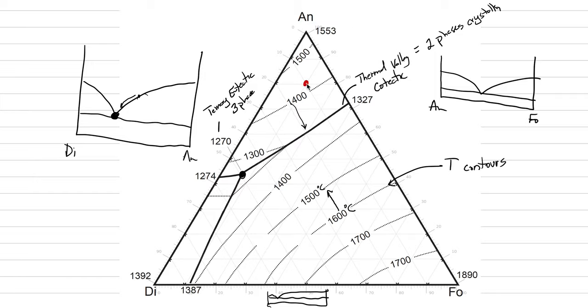If the magma is at 1500 degrees C and here's the 1500 contour, the actual temperature of crystallization — the liquidus surface — is between 1500 and 1400, so it won't crystallize anything until maybe 1420. As soon as we hit 1420 on a cooling pathway, we're going to crystallize something — whichever end member of the triangle we're closest to, not separated by a valley. In this case we would crystallize anorthite, and the composition of the melt would drive away from anorthite down topography until we get to the cotectic.